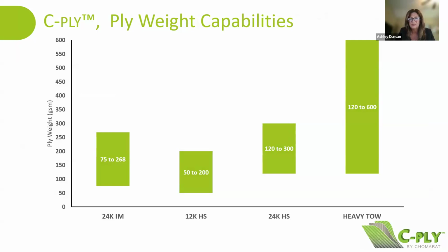I like this slide. It's a great illustration of ply areal weight capabilities relative to fiber tow selection. Starting with a 12K fiber, for example, after spreading these fibers to create a tape, your ideal areal weight range can be from 50 GSM to 200 GSM per ply. In contrast, woven 200 GSM fabrics use 3K fiber, which can be more expensive compared to heavier tow fibers. For example, our C-PLY thin ply fabrics are 100 to 150 GSM fabrics that are made with a 12K fiber.